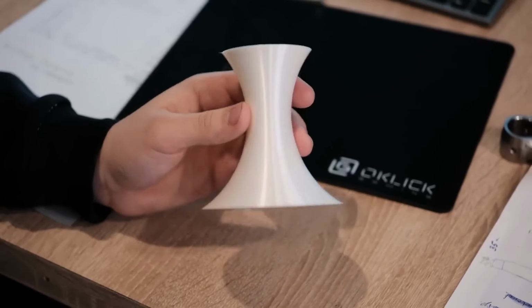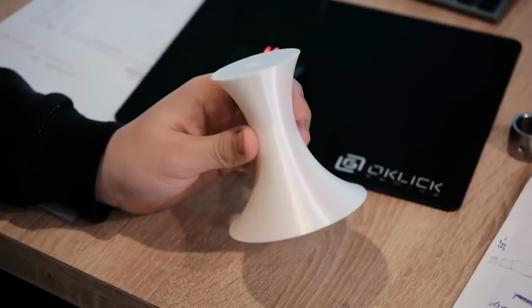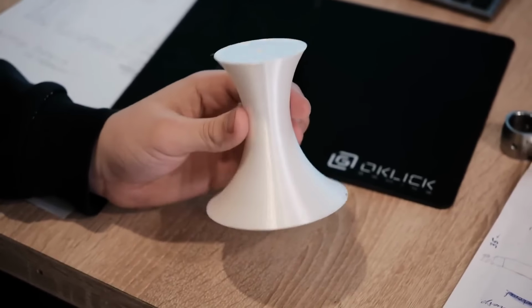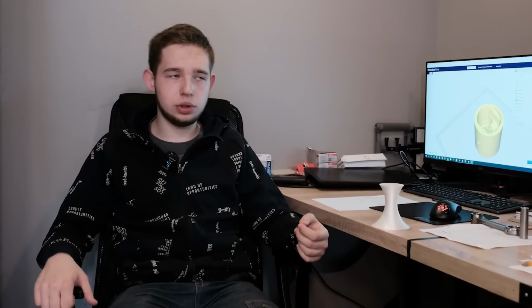The second advantage of this technology is the high surface quality of the model. Since the suspension used to apply the ceramic shell has a very fine-grained structure, with the filler being of the F1200 fraction, the resulting surface roughness can be extremely minimal. The third advantage is high-temperature casting. In other words, this technology is frequently used in industry to cast complex turbine blades and turbojet engine parts from a special alloy called Inconel.